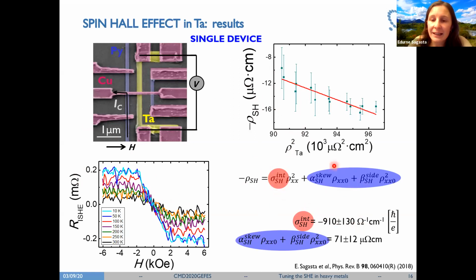And regarding the extrinsic mechanism, we see that it is positive. Again, now as the resistivity regime that we are studying is very narrow, we decided to make multiple devices and make the experiment just at low temperatures, because the variation of the resistivity with the temperature is very narrow. So then we can write the phenomenological equation for low temperatures, which basically is to write the resistivity substituted by the residual resistivity. So we can write it in this way.